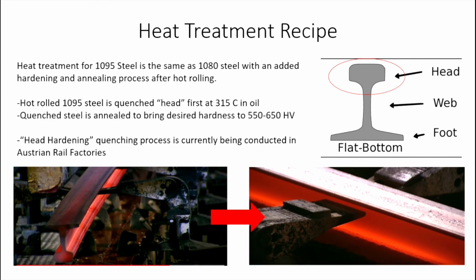However, we believe our material is superior despite the increased steps required to manufacture it. As further proof, some railroad companies in Europe currently have decided to improve their tracks via our recommended quenching and annealing techniques in a process called head hardening. During the process, the top of the rail that contacts the wheel of the train car is heated, quenched, and tempered to exhibit improved toughness and wear resistance. The bottom of the rail, that is not as affected by the quenching due to hardness penetration, is left softer than the top to help absorb vibrations and noise created by the wheels to provide a smoother ride.